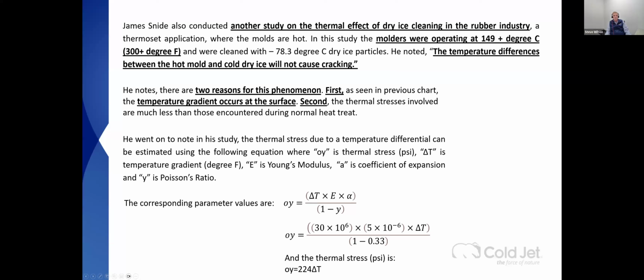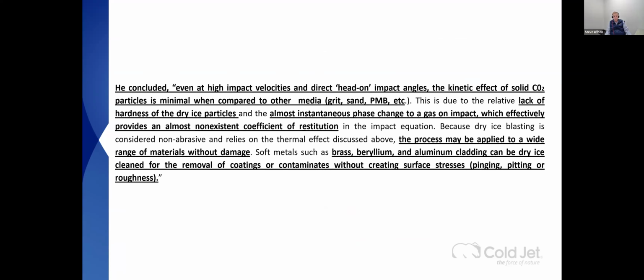He did one when the mold was hot because they had some people in the rubber industry, so it was 300 degrees hot. The temperature differences between hot mold and cold dry ice will not cause cracking. For the reasons he talked about, it's at the surface, and he went ahead and calculated the thermal stress by capturing the temperature, Young's modulus, coefficient of expansion, Poisson's ratio, and found that the amount of stress we're generating is less than when we heat treated it. So he said, go ahead. You can use this process on a wide variety of things without damage, from brass, beryllium, aluminum. Go ahead. You're not going to damage it. That's where it comes from, a mechanical and thermal standpoint.